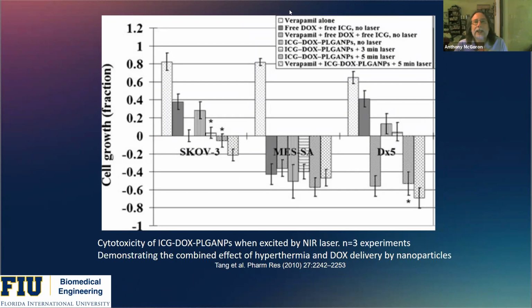Now, this is kind of a complicated slide, but we did another study with the same 3 cell lines in which we added a drug, verapamil. Verapamil is an inhibitor of P-glycoprotein function. And then also the free drug and the free doxorubicin. The third is verapamil with the free drug and free indocyanine green, the free doxorubicin and indocyanine green. Then with the 2 drugs delivered with the nanoparticles without laser, delivered with the nanoparticles with 3 minutes laser, and with 5 minutes of laser, and then also with the verapamil.